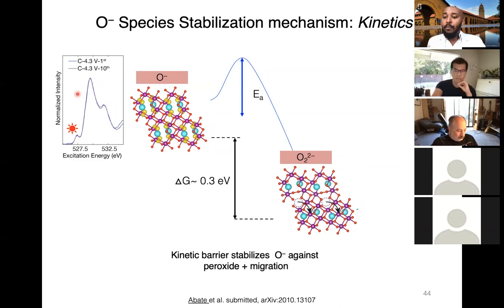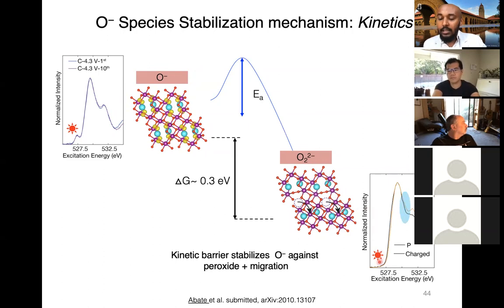However, if you perform the RIXS measurement after a couple of days, giving it enough time for the O- to overcome this barrier, you would actually have the O- species disappear, and instead you form a new feature over here that indicates that we are forming oxygen bond formation or dimerization. So this indeed confirms that there's a kinetic barrier that is limiting the system from forming a peroxide and helping us to stabilize this O- species, which is helping us to have the low hysteresis.